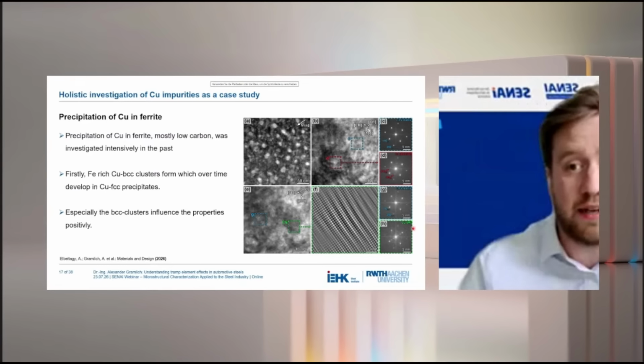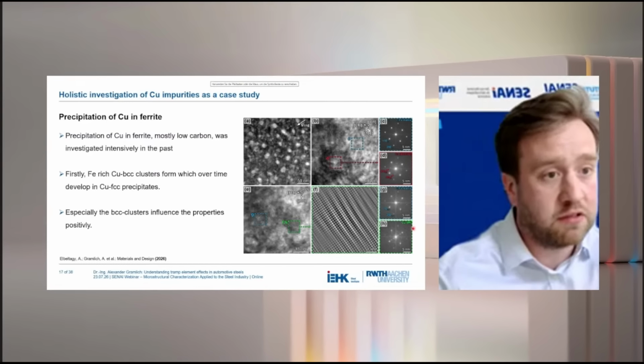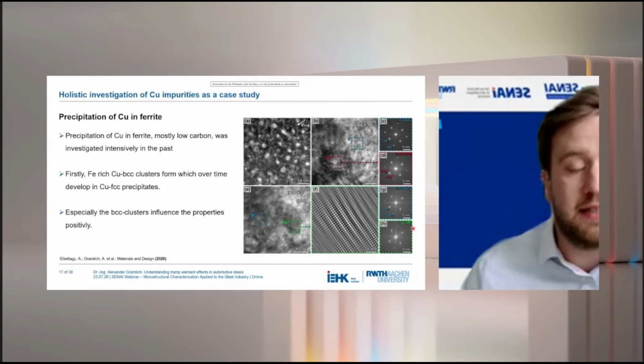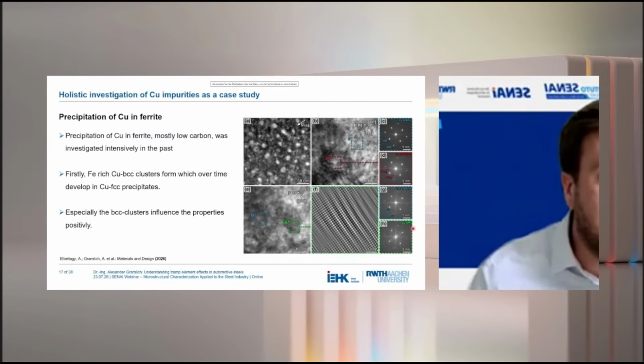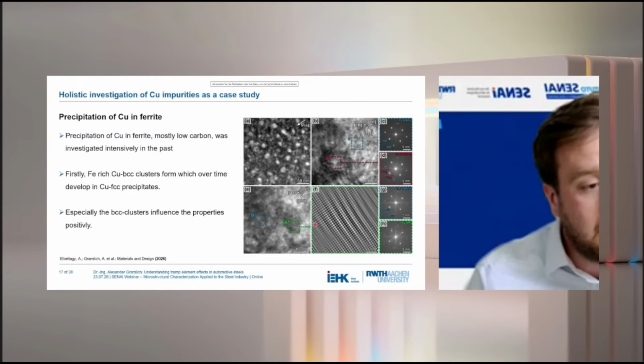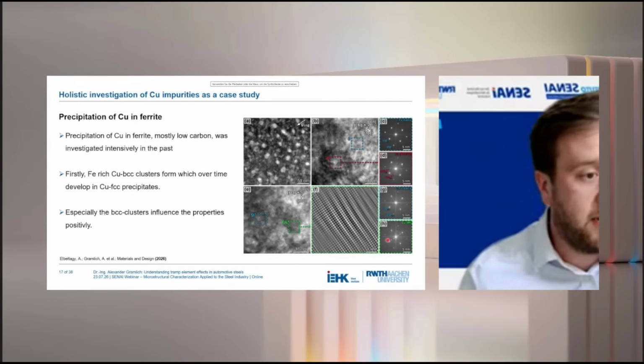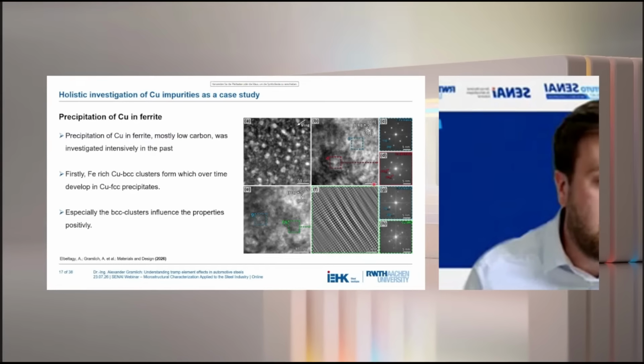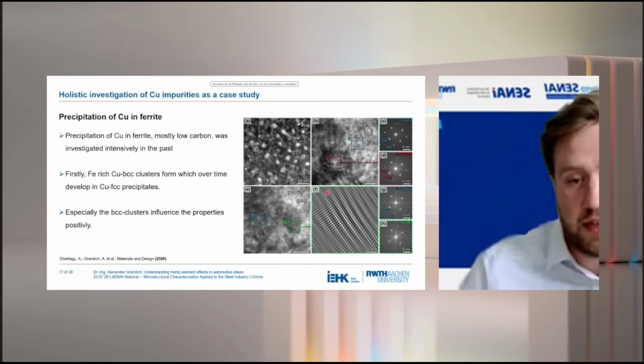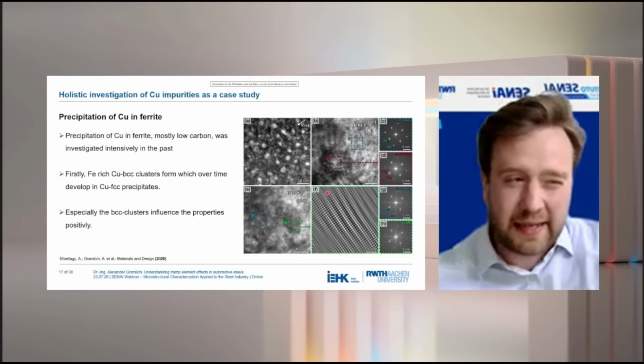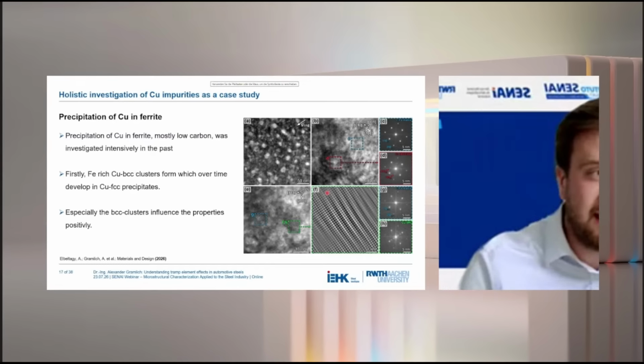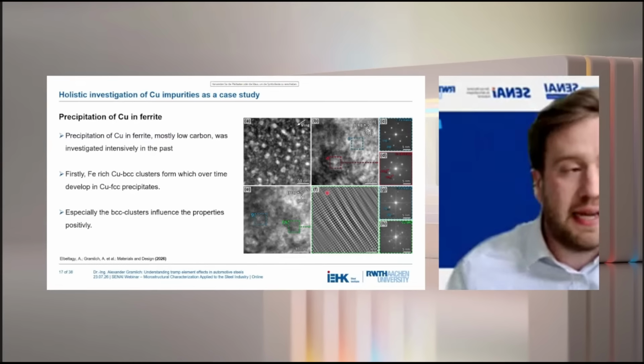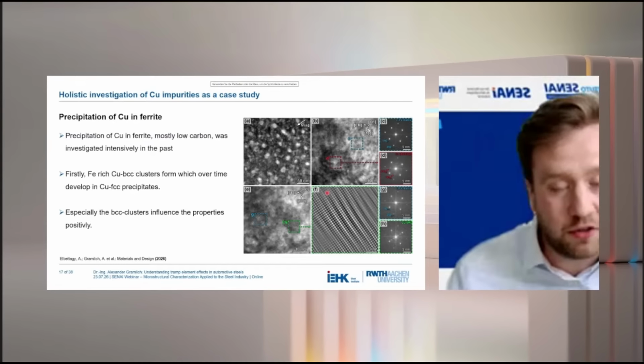When we are then diving further into the nanostructure, we can see that in the same sample, independent of the position, we can find BCC clusters, but also these intermediate precipitation states. And here we have a very nice image on the lower side where we could resolve the atomic structure. So we can see the precipitation process itself is not as easy as pointed out in most of the literature up to date.